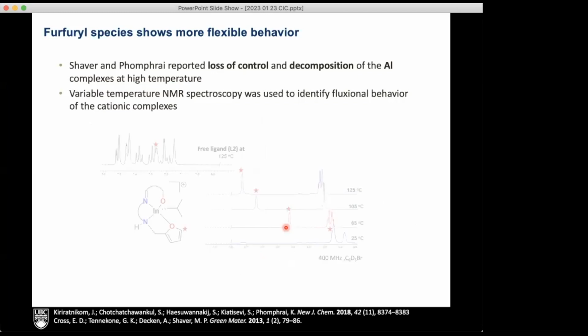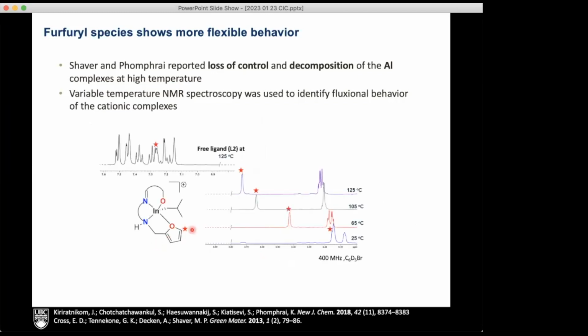And so how can we look at this? The furan, the furfuryl species, was the one that showed the most tunable behavior, because what they were able to show with this species is that when you're looking at the variable temperature NMR spectra, as you go higher, this peak here, this proton with the star, starts shifting quite a bit, all the way up to free ligand at 125 degrees C, but reversibly could come back down to 25 degrees. So this was reversible fluxional behavior.